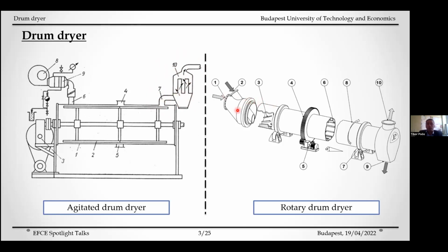The rotary drum dryer has a cylindrical drum, which is the central part of this machine, and it's made of steel, and its axis has a slope of approximately 1 to 5 degrees. The material enters at the top of the drum and leaves at the bottom. The flow direction between the material and the drying gas can be either co-current or counter-current. The drum wall can be fitted with flights of different shapes, numbers and sizes, thus modifying the contact surface between the material and the gas.